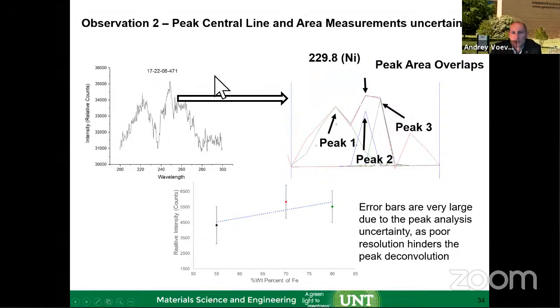And we start looking particularly at the nickel peaks analysis and the characteristic wavelengths. There is some peak overlap, which we had to work with, because multiple lines can be excited simultaneously. But the good part was that we can detect some structure in emission and correlate it to characteristic peaks. The central peak location and the measurements have certain uncertainty because of the overlap, and this is something we're working on, with some methods to do this in an autonomous way.